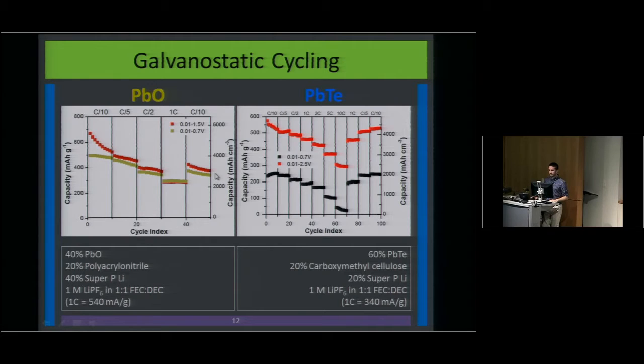With the lead telluride, we go all the way up to 10C, which is charging in 6 minutes and discharging in 6 minutes, which is pretty fast for a lithium-ion battery. Graphite itself can only go up to about 1C before it starts suffering damage. You can see that we actually maintain a little bit of capacity even at that high rate, and even more impressive, we go back to the original capacity once we go back to the slower rates.